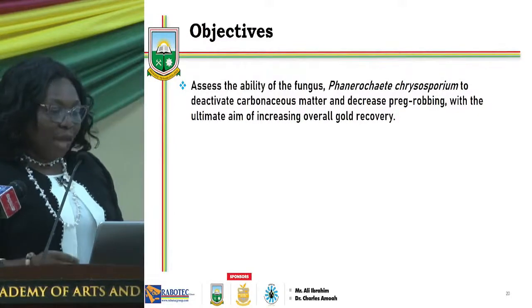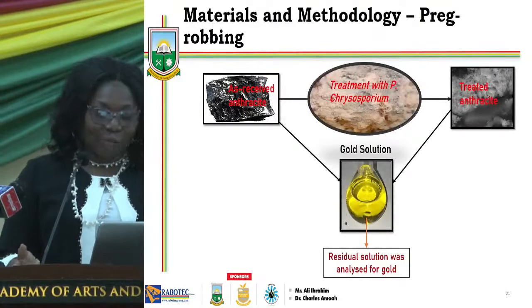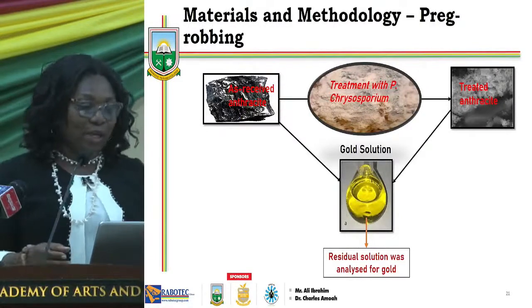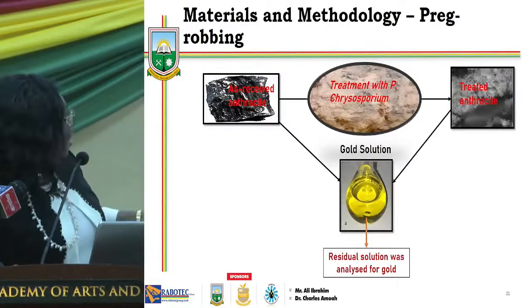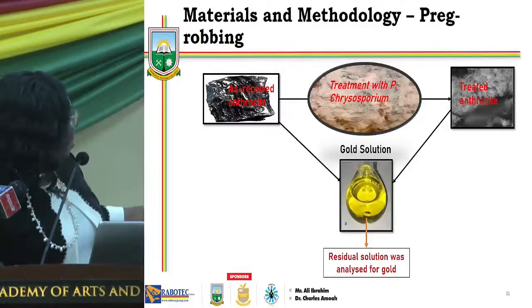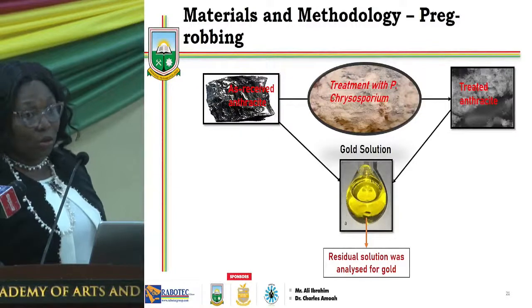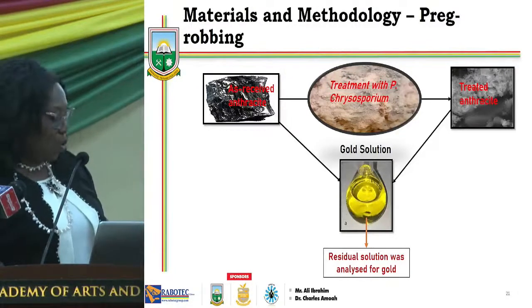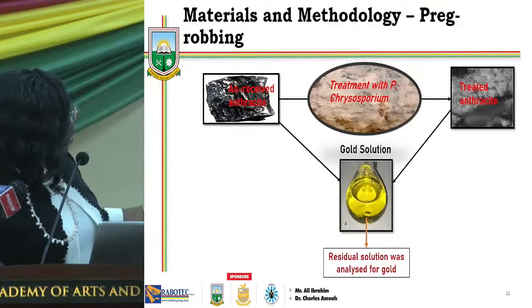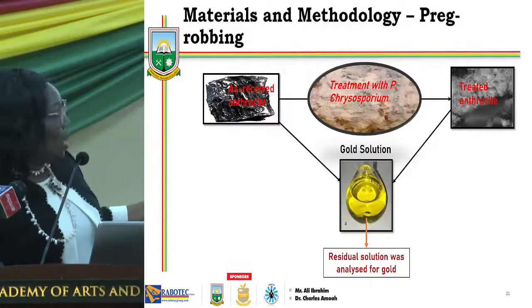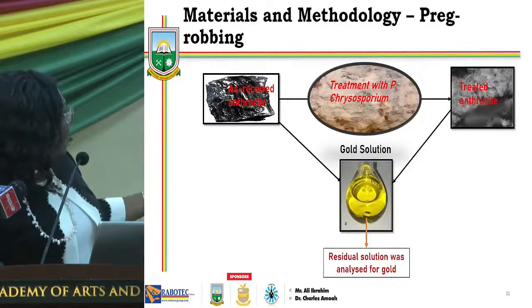So, first, I used anthracite as a surrogate for carbonaceous matter in gold ores. So, that is the as received anthracite. And then I have my standard gold solution. Anthracite is contacted with a standard gold solution to see how much it can adsorb. Then, anthracite is treated with Phanerochaete chrysosporium. So we get the treated anthracite, which was also contacted with standard gold solution.